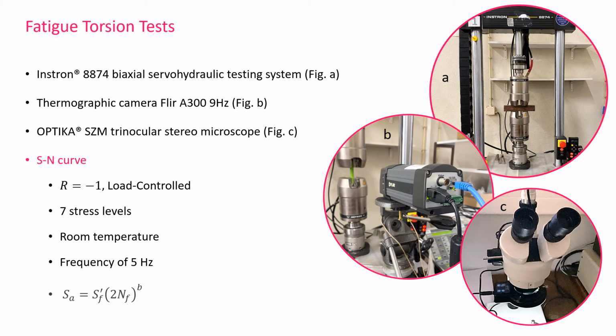Fully reversed, load-controlled in high-cycle fatigue regime tests were performed and 7 stress levels with only 1 repetition were chosen and assessed at room temperature with a frequency of 5 Hz. Specimens were subjected to constant amplitude loads and the corresponding reversals to failure were plotted on a Basquin curve. Fatigue properties were obtained by fitting the experimental data to the equation developed for the high cycle fatigue regime displayed on the screen.